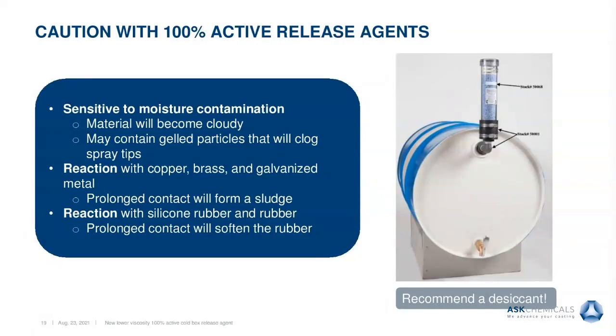100% active release agents are prone to moisture contamination. This is visible in the release agent if the material appears cloudy, containing gel particles. These particles may clog spray tips. 100% active release agents will also react with copper, brass, and galvanized metal, forming a sludge. The material may appear greenish-blue in color. A reaction will also occur with silicone rubber and rubber, causing the rubber to soften.